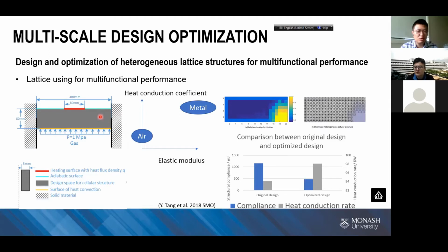In the past, if the structure was made of pure metal and you put the heat source here, part of the heat would go to the gas, but other heat would go to the sidewall because the sidewall temperature is really low. In this design, we want to use lattice structures to provide heat insulation. A lattice structure is a combination of air and metal. Metal has a high elastic modulus and high heat conduction coefficient, but air has almost zero elastic modulus and a low conduction coefficient. We want to use lattice structures to combine the two properties in different places.